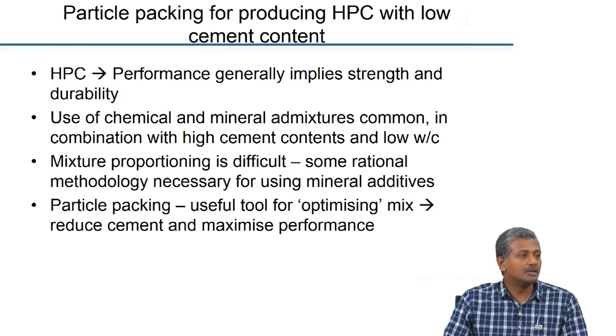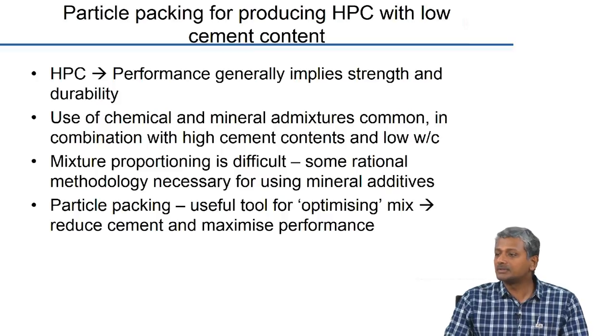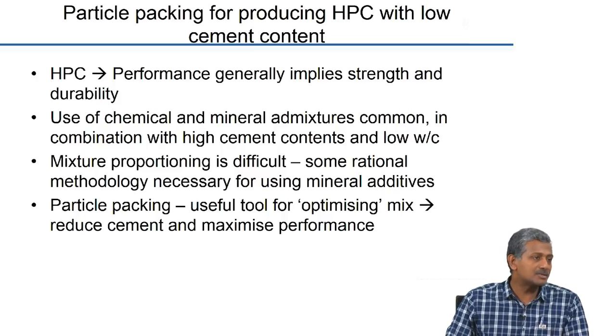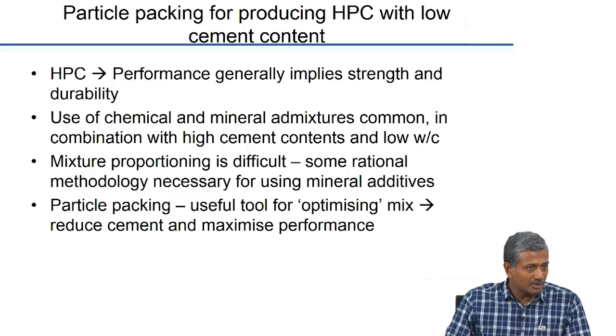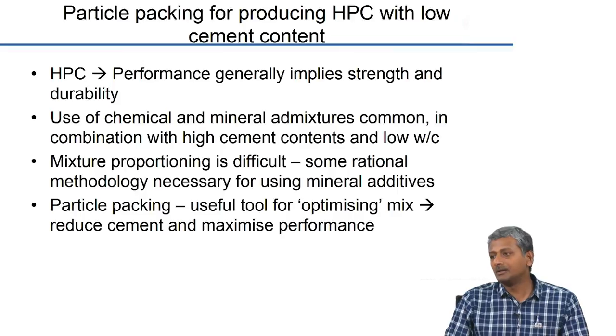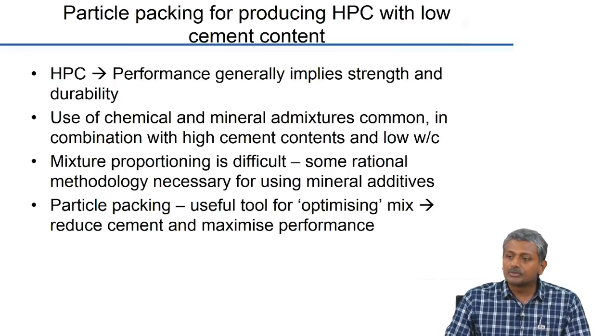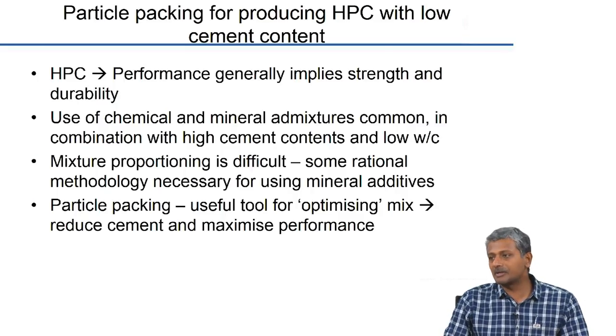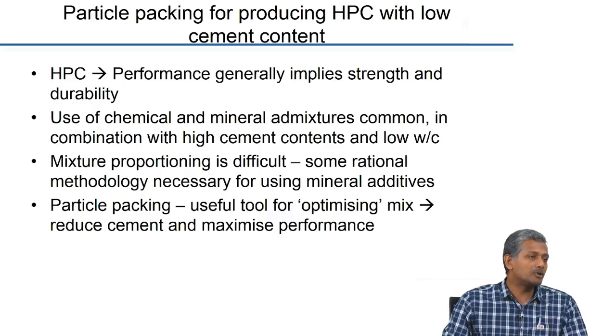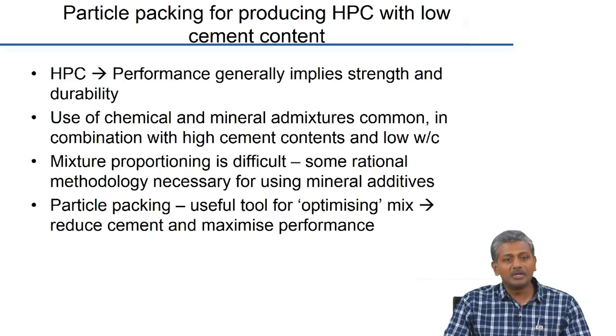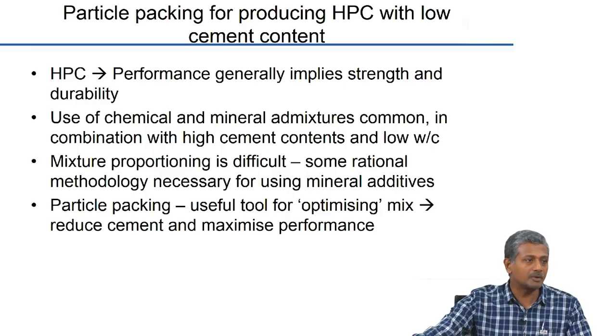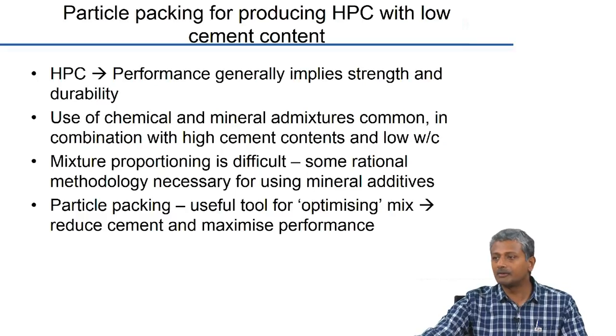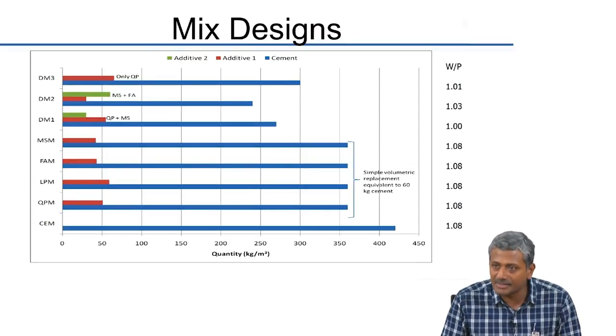There are obvious issues when high cement contents are used — you have more potential for shrinkage, greater thermal effects, and increased cost. Mixture proportioning of such systems becomes quite difficult. This is where tools like particle packing could be useful to optimize the granular constituents and minimize the amount of cement required. This was actually part of an M.Tech project done by one of the students, which resulted in a couple of papers — a link to these will be given at the end of this chapter.